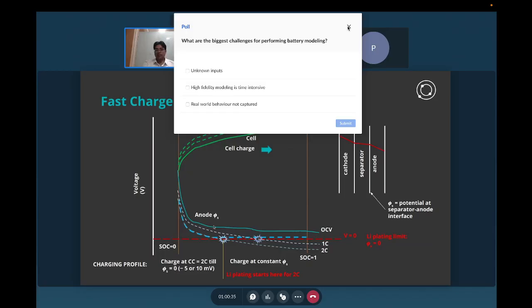And initially, if you look at the anode open circuit voltage itself, it might not be going below zero during the charging and discharging process, but because of the overpotential drops, you would see that depending on the C rate combinations that you are running, charging or discharging the cells at, you would hit this zero line. This is called the plating line, and beyond which the plating will start.